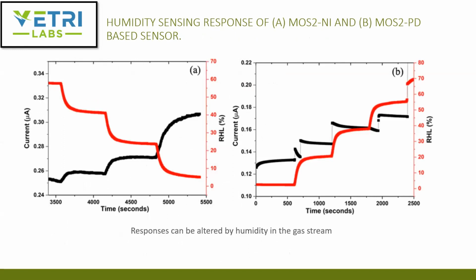They also looked at how humidity plays a role in the background noise. They've calibrated the nickel and the palladium sensor against different levels of humidity. They measured the current response and compared that to the actual sensor response at each of these conditions. And they show that the sensor can be interfered with or be cross-sensitive to humidity in some cases. So from a device usability standpoint, the humidity correction has to be happening as well. But on a positive note, you can sense humidity in a gas stream. There are devices today that need gas or humidity sensing, so this could be a possible way to get humidity, at least up to 70%. There's a chance of detecting humidity in gas streams.